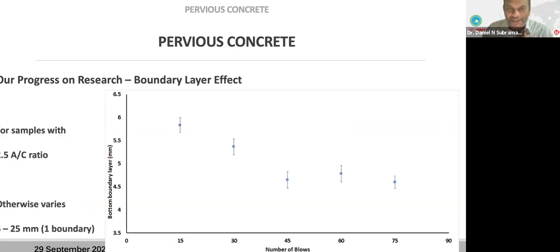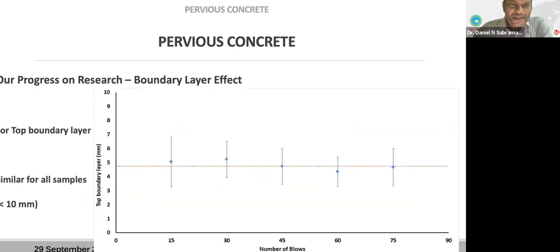So this is showing the variation of how it is changing with the blows. So 30 or 45 somewhere in between, and then after that you see a stagnant level. Right. So this is for the top boundary. What we discussed earlier was the bottom boundary layer. Now this is about the top boundary layer. The top is not having any impact from a rigid surface, because there is no surface on the top. So this is the effect of how we pack.